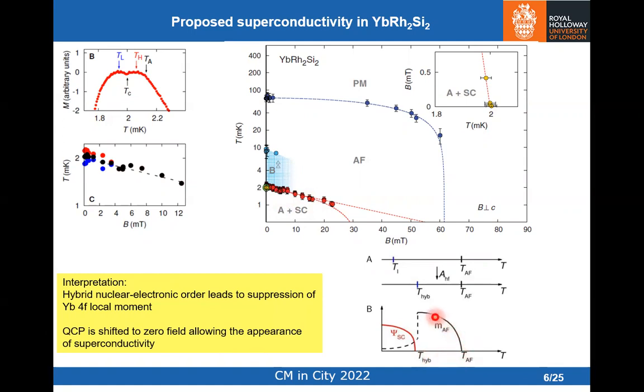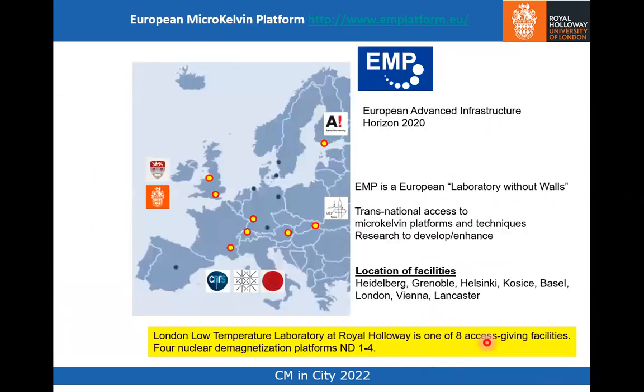You can see this here at this temperature. Here's the antiferromagnetic order parameter that's developing below the Néel temperature, 70 millikelvin. And then down here at T sub hybrid, there's another transition in which the antiferromagnetism weakens and the superconductivity appears. This was the hypothesis of that work. The narrative around it was that, over here, you've got a quantum critical point. Somehow that quantum critical point has been shifted to low magnetic fields by this destruction of the antiferromagnetic order by this hybridization interaction. And this is a hypothesis that we wanted to test in our own experiments.